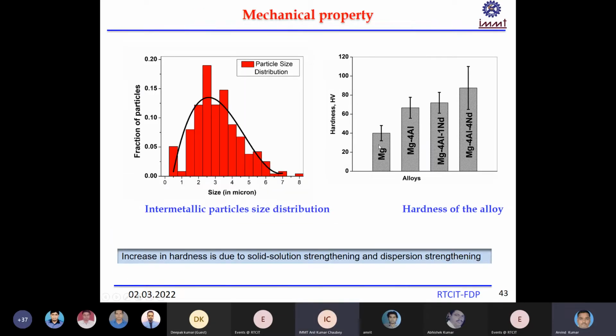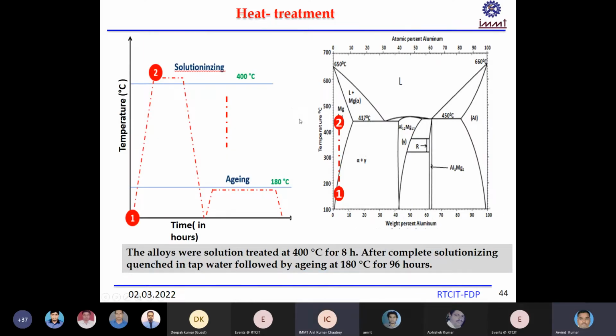So here you can see how the hardness increases with the neodymium percentage, and this is the fraction of the intermetallic phase distributions, how the phases and their different sizes vary with adding neodymium and forming Al2Nd and Al11Nd3 phases. So these aluminium neodymium phases increase the strength as well as reduce the grain size. That's why we are getting strength and hardness here, which also indicates that strength is increased by adding neodymium.